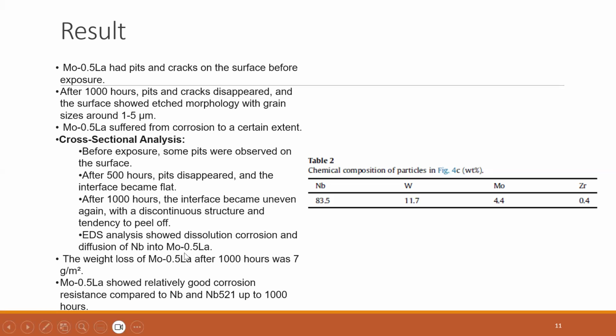And the weight loss of the molybdenum alloy after 1000 hours was 7 gram per meter squared, and molybdenum alloy showed relatively good corrosion resistance compared to niobium and niobium alloy up to 1000 hours. So in table 2, the chemical composition of the particle in weight percent: niobium is 83.5 weight percent, W is 11.7 weight percent, molybdenum is 4.4 weight percent, and zirconium is 0.4 weight percent.